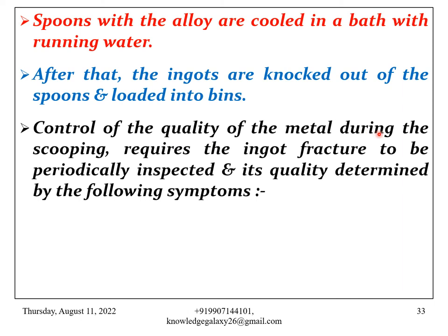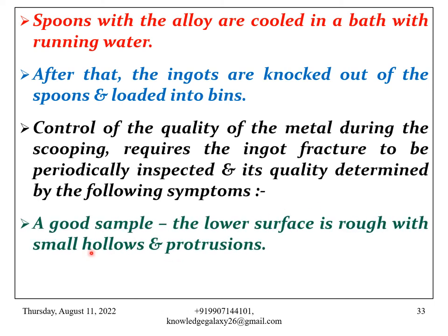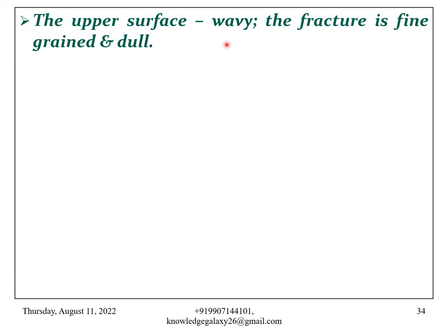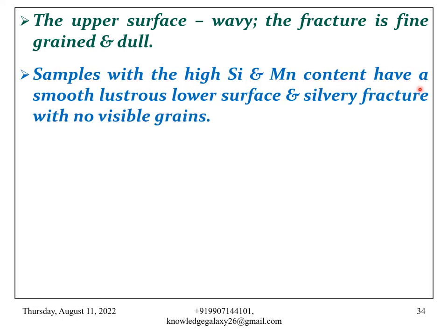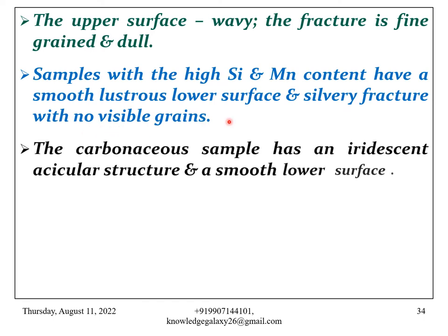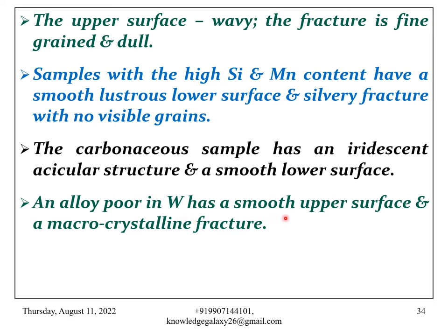Control of the quality of the metal during the scooping requires the ingot fracture to be periodically inspected and its quality determined by the following symptoms. First, a good sample has a lower surface that is rough with small hollows and protrusions. The upper surface is wavy and the fracture is fine-grained and dull. Samples with high silicon and manganese content have a smooth, lustrous lower surface and silvery fracture with no visible grains. The carbonaceous sample has an iridescent acicular structure and a smooth lower surface. An alloy poor in tungsten has a smooth upper surface and a macro crystalline fracture.